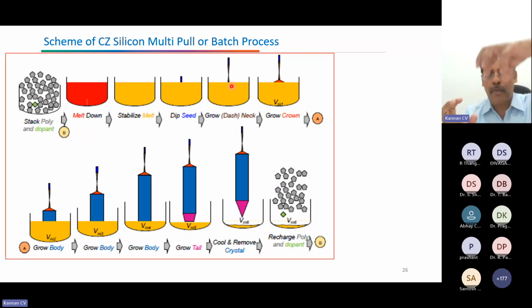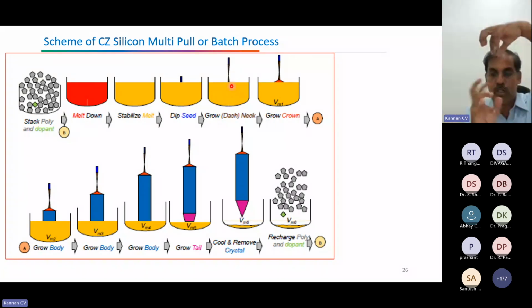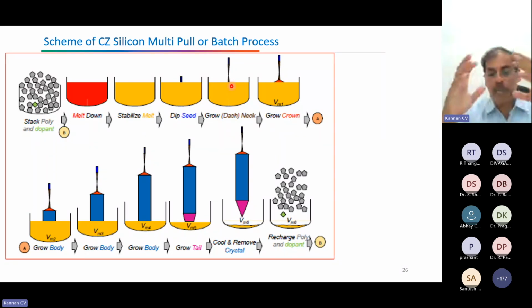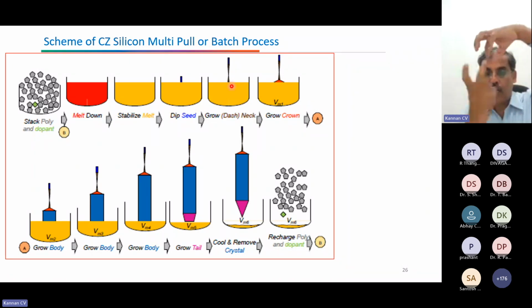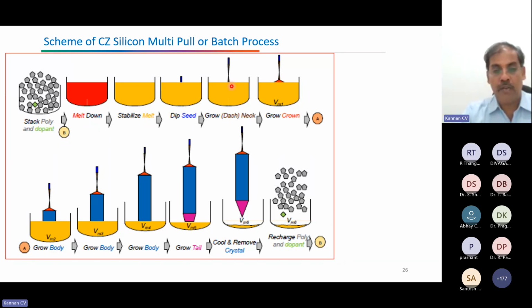So by pulling speed, rotation speed, and crucible rotation, you can maintain the diameter. What is the size you want? Everything you can control. What is the length you want? Everything you can control through pulling speed, rotation, and crucible rotation also. Automatically, after some time, the crucible level will come down slowly. When the melt is converted into solid crystal, the melt volume also comes down, and at one stage, with a very small amount left, you have to take it out.